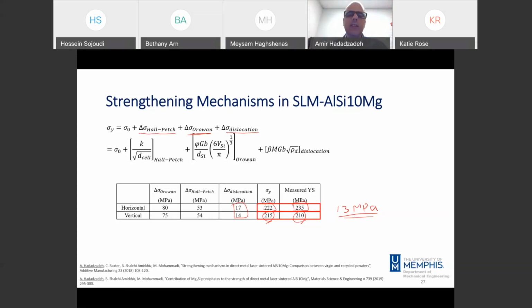How do we eliminate defects like impurities, cracks, or undesired surface roughnesses in the SLM method? Okay, that's a good question. Those defects usually are eliminated by controlling the process parameters or developing optimum process parameters.